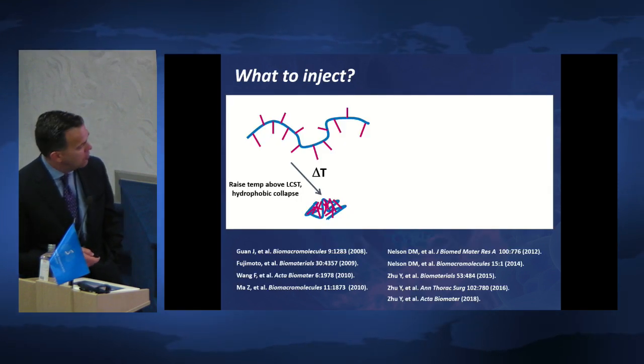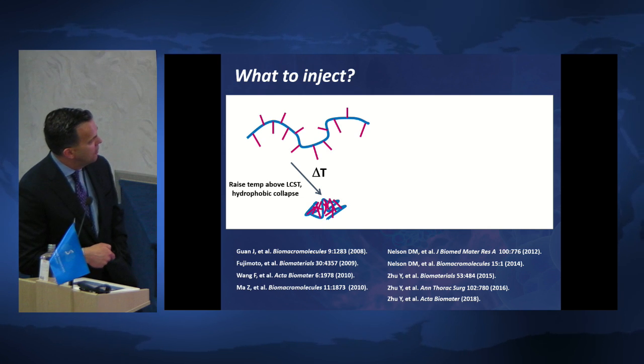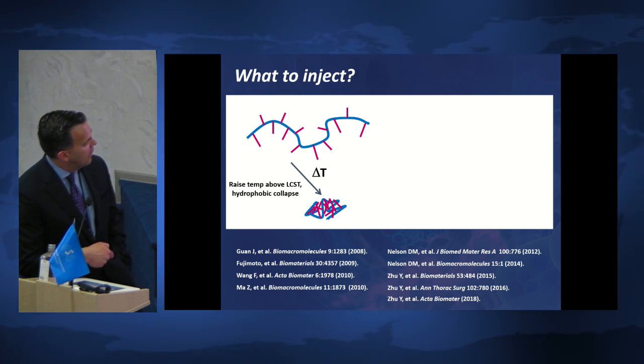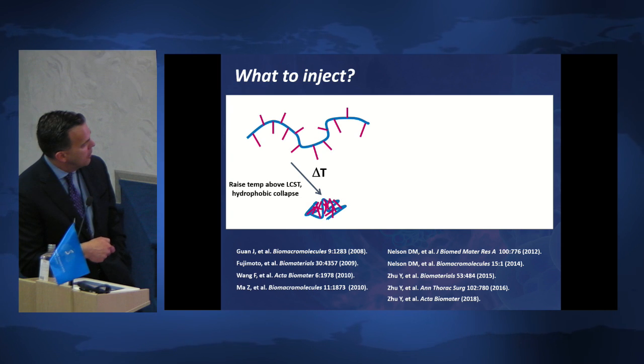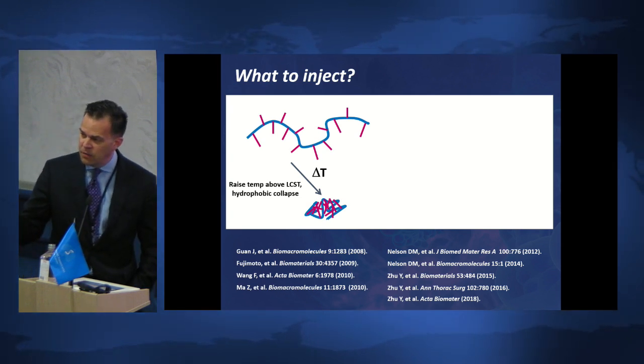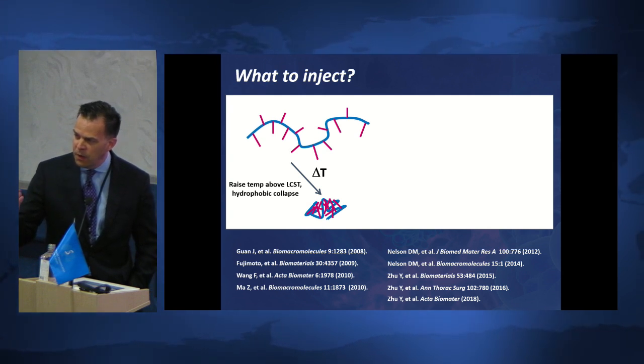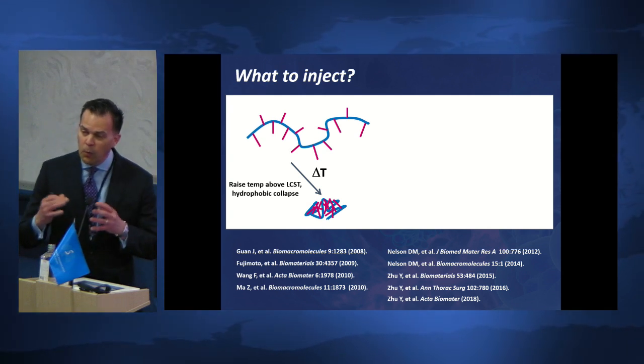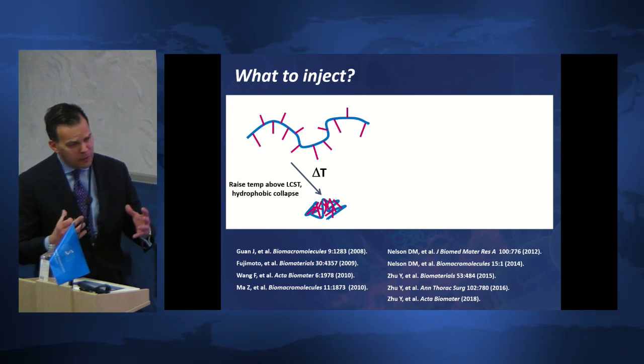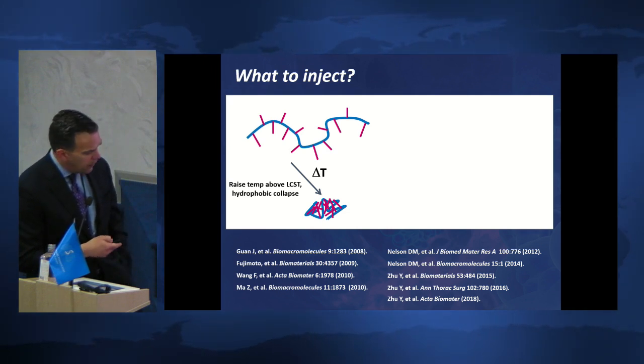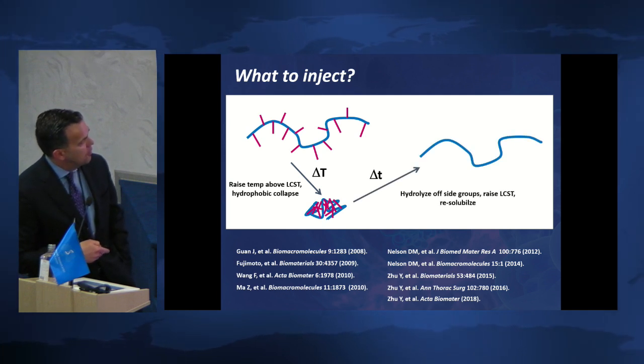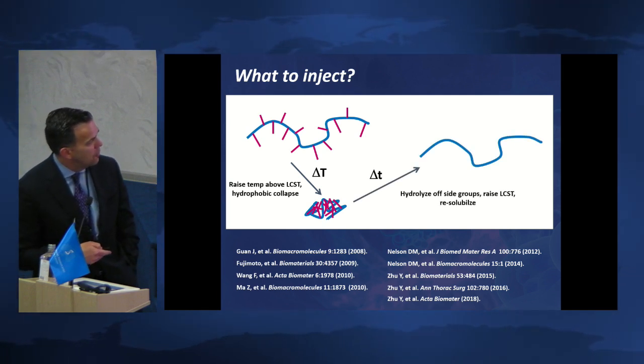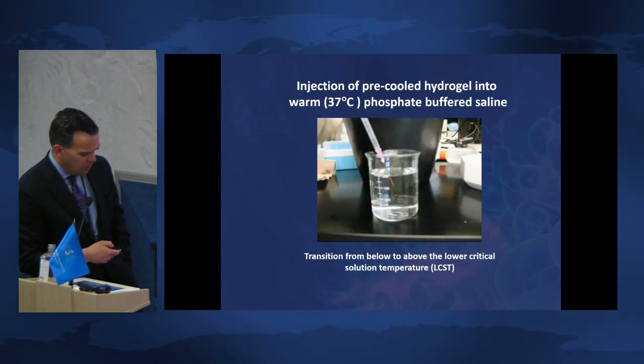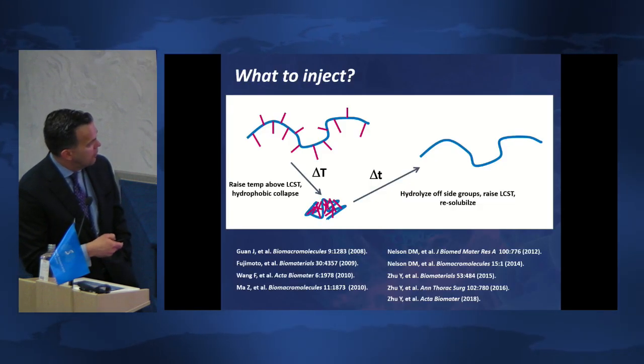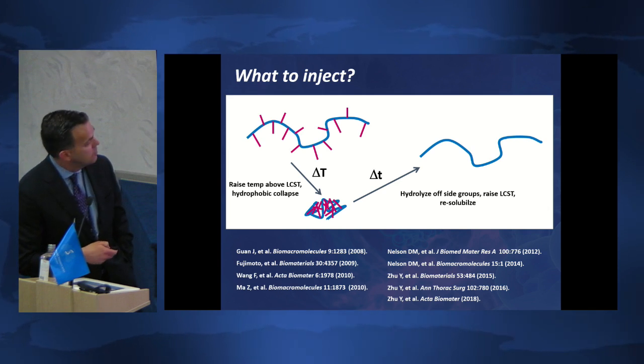Again, I won't show you the polymer chemistry here, but the idea is to use thermodynamics so that this polymer in the blue with the pink attachments will collapse. Due to entropy, it will thermodynamically collapse into a stiff gel, which is what we want. We want a relatively stiff gel in the cardiac wall. But over time, those pink segments, which have ester bonds, get hydrolyzed off. That raises the lower critical solution temperature, and then it becomes soluble again.